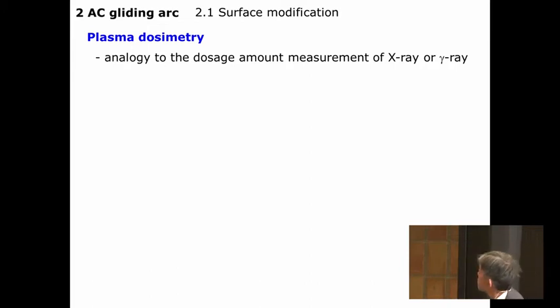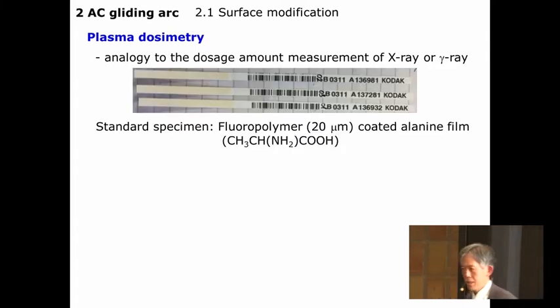It is related to what we call plasma dosimetry. It's an analogy of the dosage amount measurement of X-ray or gamma ray. And the specimen is alanine. It's a kind of standard material for this area. And the idea is why not use it for measuring the dosage of the plasma. However, we realized that it is coated with fluoropolymer. It's probably PVDF, 20 micrometers. It's very thick. Therefore, I doubted if there would be any effects. But anyway, we tried it.